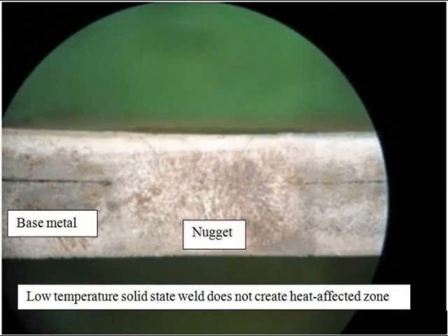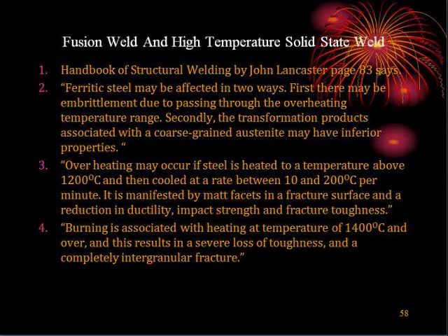And there are no dendrites, no heat affected zone in a low temperature weld. According to the Handbook of Structural Welding by John Lancaster, page 83, it says ferritic steel may be affected in two ways. First, there may be embrittlement due to passing through the overheating temperature range. Secondly, the transformation products associated with the coarse grain austenite may have inferior property.